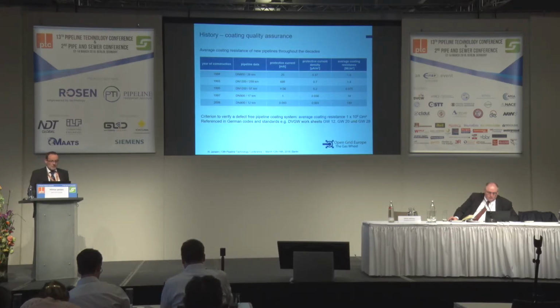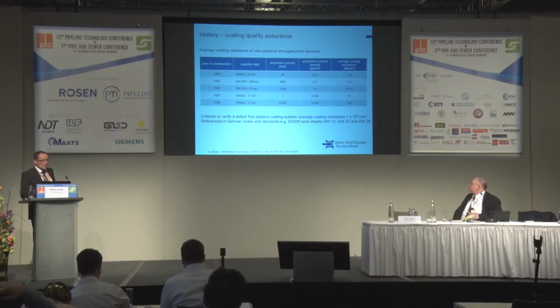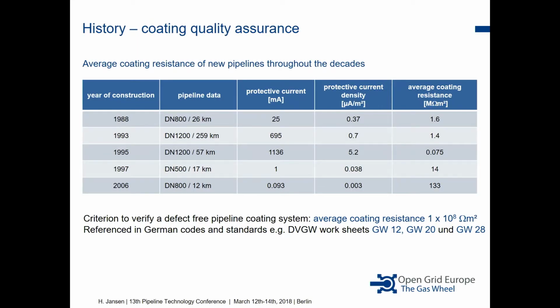I would like to give a small look back to the coating quality. Average coating resistance is a cathodic protection figure that gives you a benchmark of the coating quality you achieve in the field. And what I've done here in this table is summarize some pipeline commissioning data from the CP data and the year of construction.